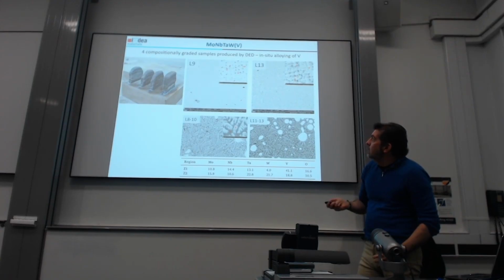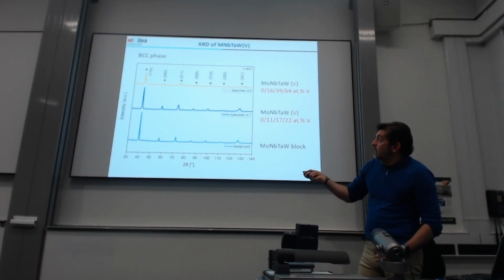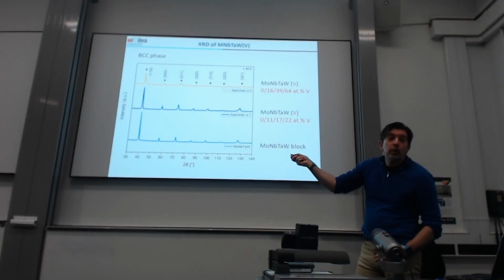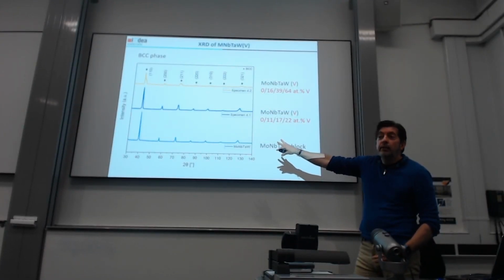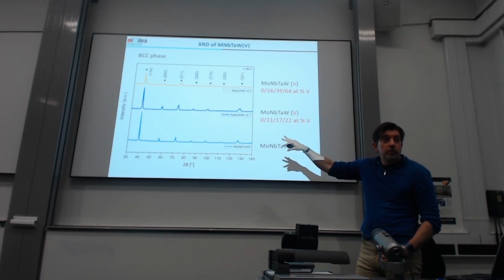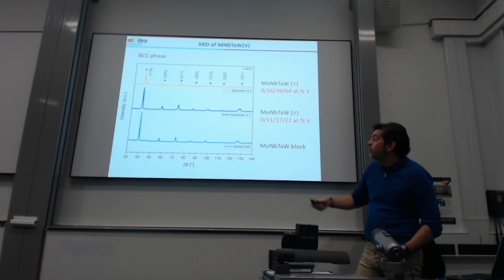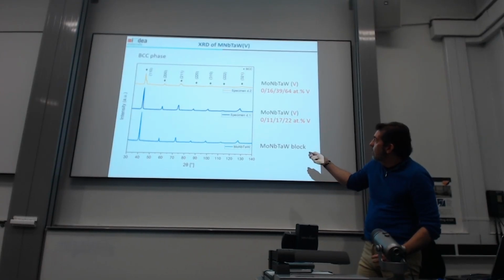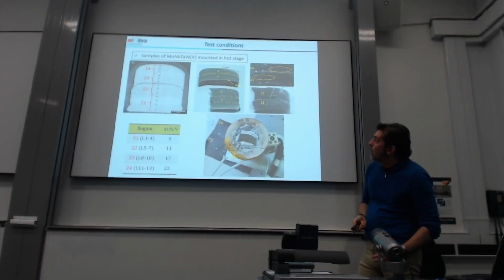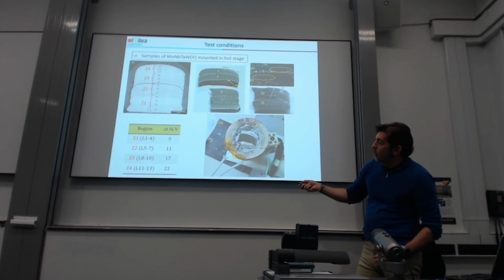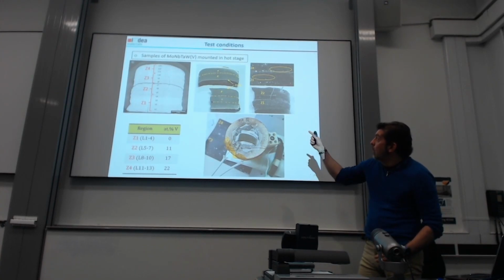But anyway, I did the test in one of them. It keeps the BCC structure, with some preferential orientation for the 110. The XRD spectra looks exactly the same as the powders, so we can keep the BCC. And I looked at these compositions for the nanoindentation. I got this one. We have 4 different zones with different vanadium content: 0%, 11, 17, and 22.